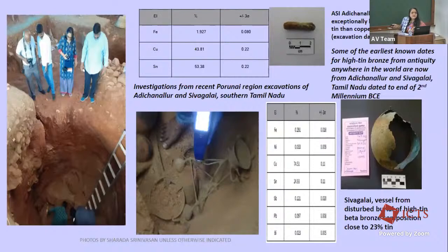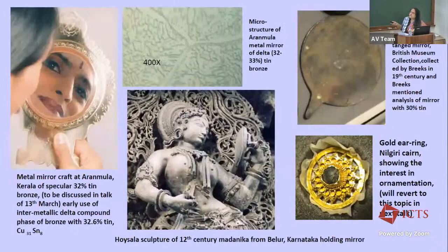And we took our portable XRF machine, and this is one of the pit burials here in Adichanallur, and went down it. And in Sivagalai also, we found the use of this beta bronze composition. And in Adichanallur, we also found a fragment which had more tin than copper, 53% tin. So clearly, by the end of the second millennium, there was the use of high-tin bronze already in South India. It's a topic I'll come back to tomorrow because it again raises a lot of other questions, but we won't handle it all here.